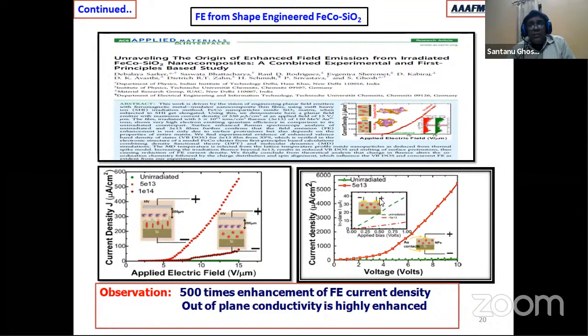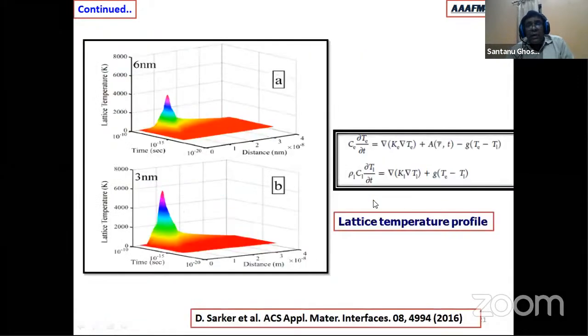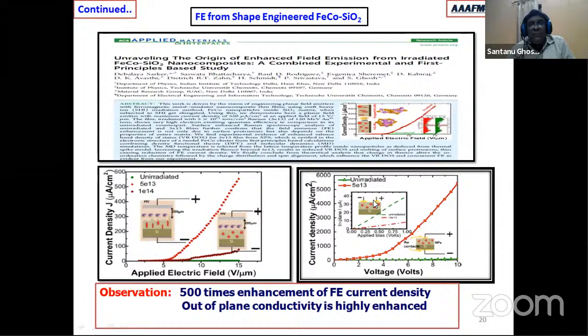So what we did actually was the out of plane resistance IV measurement. In that also, in out of plane IV measurement, what we have seen is the current density is much higher as compared to in plane current density. So this clearly tells that whenever there is an elongation of the particle, there is an easy path of electron flow.